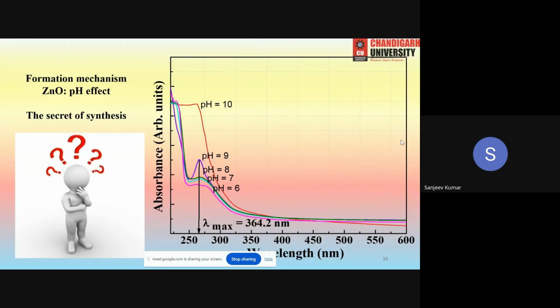Okay. Now, most of the time we are unsure whether our nanoparticles are formed or not. So you can use the in situ UV-visible spectroscopy technique. I have set pH 6, 7, 8, 9 and 10 in this graph. And you can easily see that at pH 9 we have a very crisp and clear peak. This peak shows that we have achieved the optimum reaction conditions, like pH 9, which is the best for the formation of the particle of choice. So you have to optimize this.